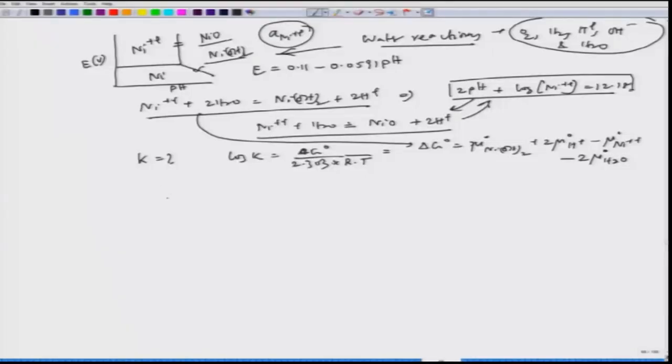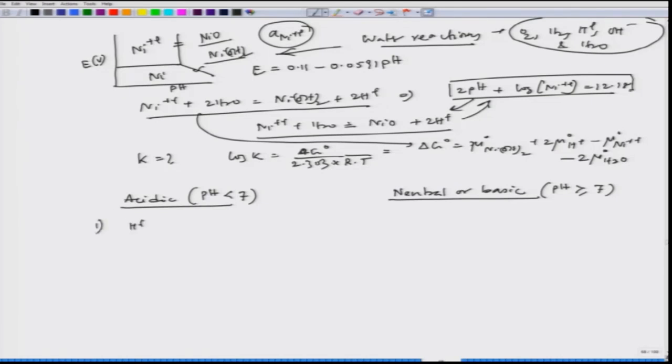Now, if we write down those equations, first is acidic and then neutral or basic. So, this is pH less than 7. And here pH greater than or equal to 7. So, there are two types of reactions, and in those two types we have two reactions each. One is H plus plus 2e equal to H2, where the equation would be E equals minus 0.059 pH, where E0 equal to 0. Two, O2 plus 4H plus plus 4e equal to 2H2O, and here you see that only H plus ions are involved. So, there